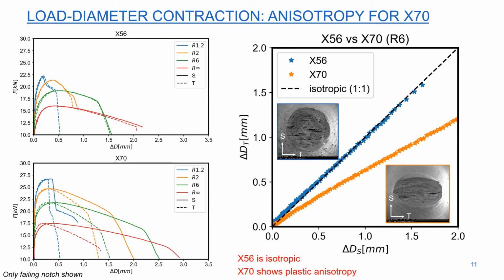The figure on the right explicitly shows the diameter contraction for both steels in both directions, clearly showing a difference between the isotropic X56 and the anisotropic X70. The presence of anisotropy is another important challenge in calibrating the damage model.